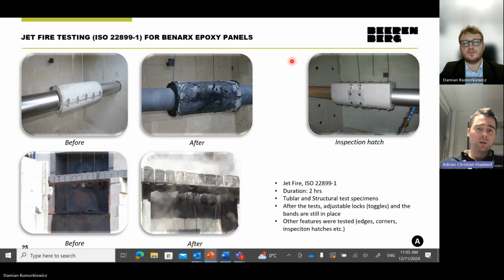Here you see a typical cylindrical box to the left. We did an extra test with an inspection hatch here to the right side. On the bottom, you will see square-sized panels, which were fabricated for a cable tray application. And we also do structural tests, as we showed in the previous pictures.